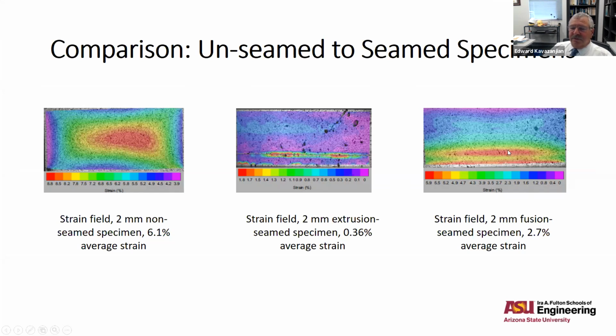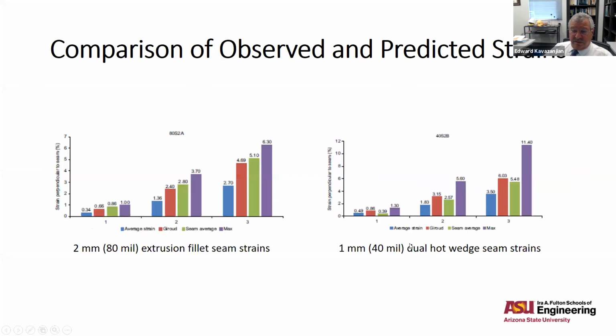Here are the results for a fusion seam, a little bit more uniform. This had an average strain of 2.7%. In the middle of the coupon, we're getting up to 5%, an amplification factor of 2 along the seam. So a little bit more uniform, a little bit less amplification than the extrusion seam, but still some significant strain amplification.